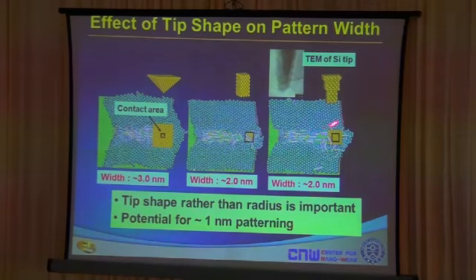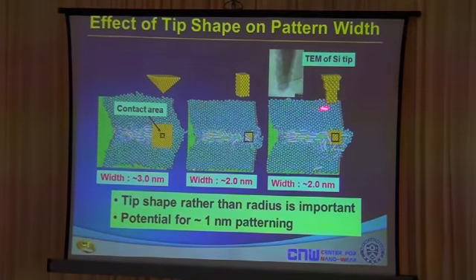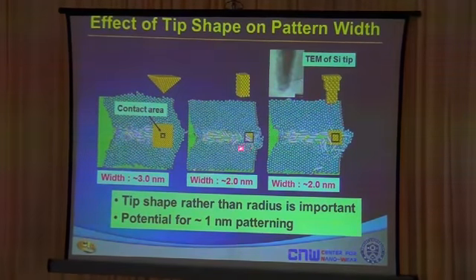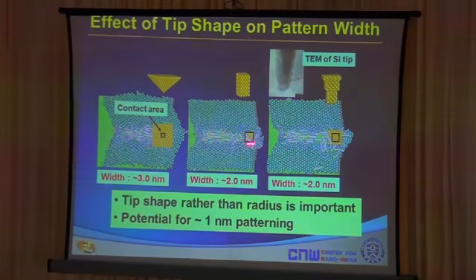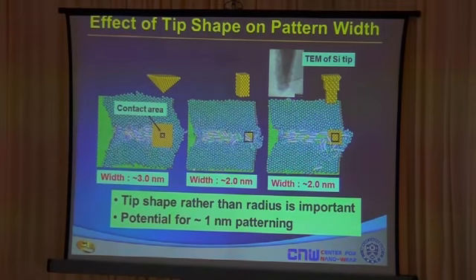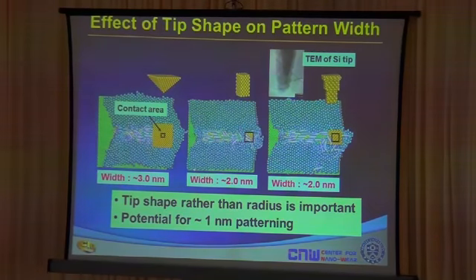What we further did was to see the effect of the tip's geometry on the pattern width we got. This is a sharp tip, and these tips represent a more realistic tip geometry. This is the TEM image of a silicon tip, so this was modeled to represent a real tip better than this particular tip. In the end, we see that during simulation, we're able to achieve widths on the order of about 2 to 3 nanometers. Practically, we're not able to achieve this, but theoretically, we hope this process was able to create patterns at the few nanometer level.